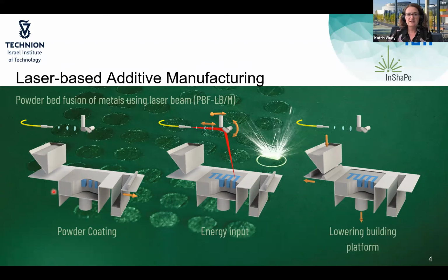And what is happening? The first step in powder bed fusion is that you need to apply a powder layer, and this is the powder coating step. And afterwards, you need to fuse this powder layer with the energy input, and the energy input in our case is given here by an IR laser which melts the metallic powder material, and you generate a melt pool. So the project is actually focusing on this energy input step and how to tailor the energy input, but I will describe this later. And the last step is the lowering of the build platform, and then afterwards a new powder layer is applied, and all these process steps are repeated until our final component, which would be the TUM logo here, is created. So that's for those who are not familiar with the process.